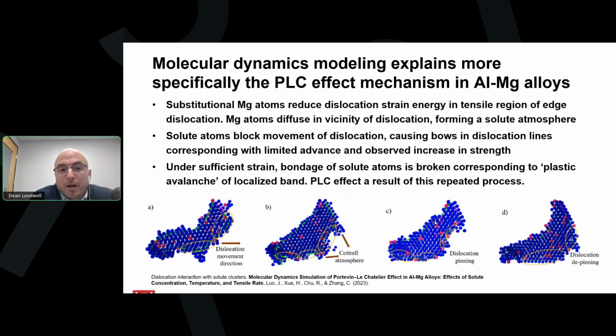Now, Liu et al. developed a model for this behavior that I find really clarifying. Beginning with figure A on the left, we have an aluminum magnesium alloy in tension in the elastic region. The magnesium solute atoms here, depicted in red, are uniformly dispersed throughout the aluminum matrix, which is colored in blue for this illustration. As the specimen is plastically strained, these magnesium atoms, which are slightly bigger than the aluminum atoms, diffuse toward the tensile region of edge dislocations in the metal. Here they pin further dislocation movement until the bondage of those solute atoms itself is broken.